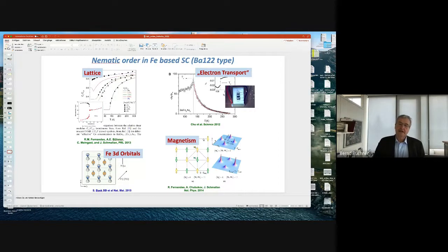And there's another class of experiments which has developed in these systems, and this is strain-dependent transport. I will show you more data on that later on. So what you do there, you take a single crystal, glue it on a piezo crystal, and then you apply a tiny strain, and you measure how the resistivity changes. And if you had a usual metal, then nothing would happen.